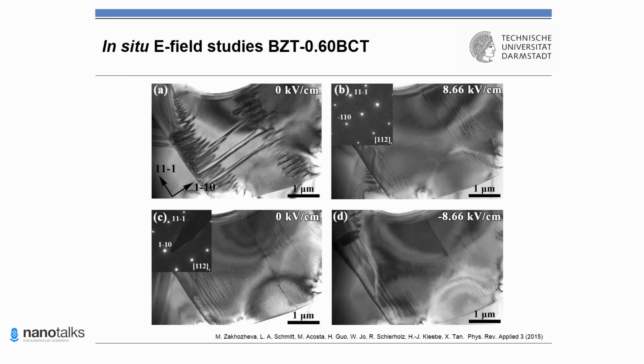Okay, let's have a look at the trigonal composition. For the BZT-xBCT, we performed the same kind of experiment. The grain was imaged along the 112 zone axis, and at zero field we saw such lamellar domains. Increasing the field up to 8.6 kV per centimeter induced the appearance of a nanodomain state. However, in this case, we didn't get our single domain state even at 12 kV per centimeter. On field removal, we saw a nanodomain state as well at zero field, and after changing polarity, basically no crucial changes appeared up to 8.6 kV per centimeter. However, we actually got our single domain state, but it happened at 20 kV per centimeter, which is very huge. So why does the single domain state occur at much higher poling field for this composition?